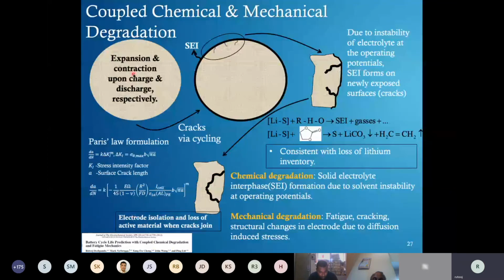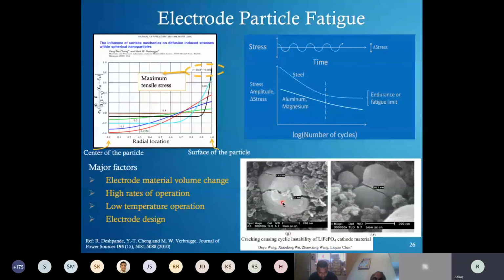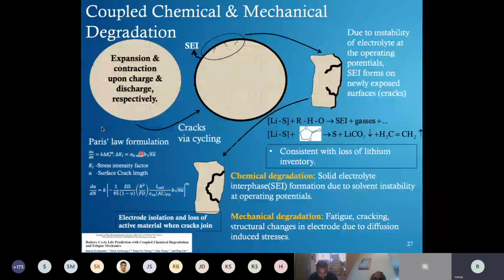So what's the implication of these stresses? The electrode particles may gradually crack. Now there is this electrode particle, and there are always some defects to start with on a particle. As you are doing charging and discharging, these micro cracks will gradually grow. Now what happens is, whenever there is a crack, new electrode surface would be exposed to the electrolyte. So electrolyte can just seep into this crack, and it will react on the surface and then basically form new SEI or have more side reactions on this surface. So there is more loss.